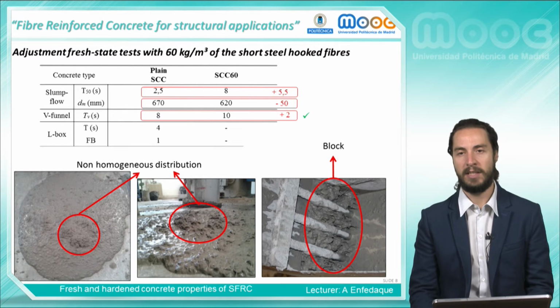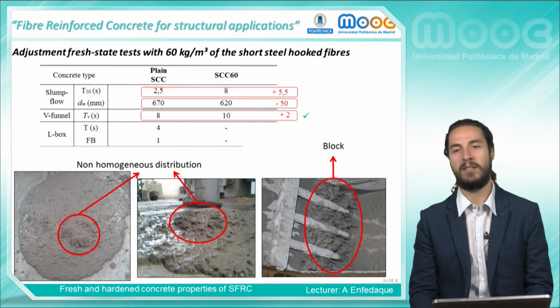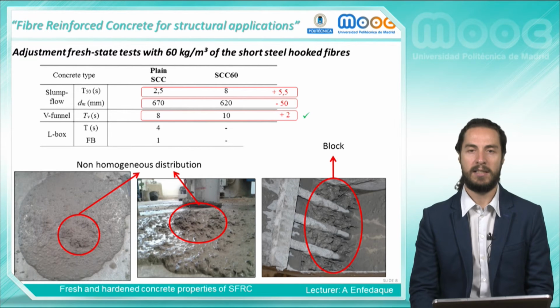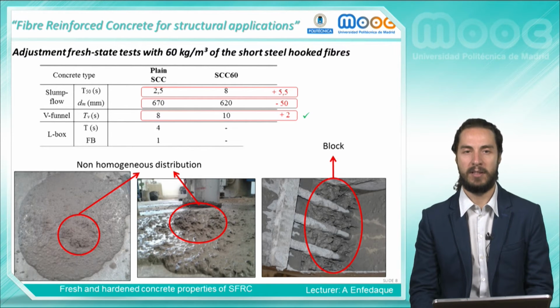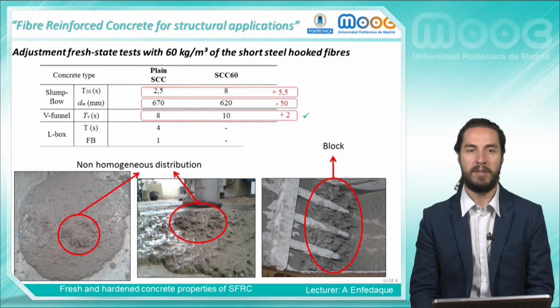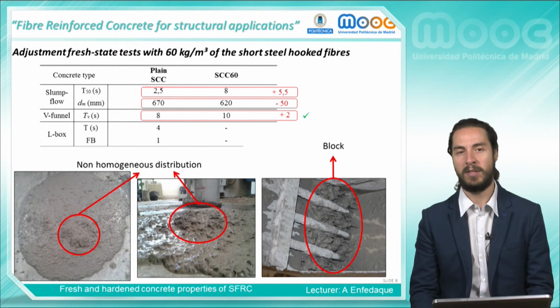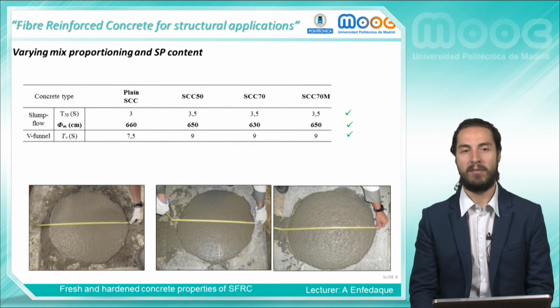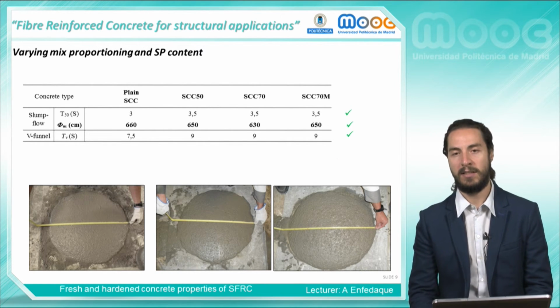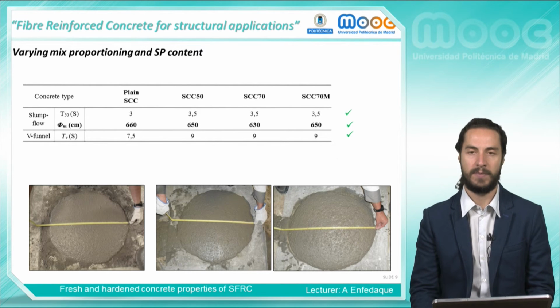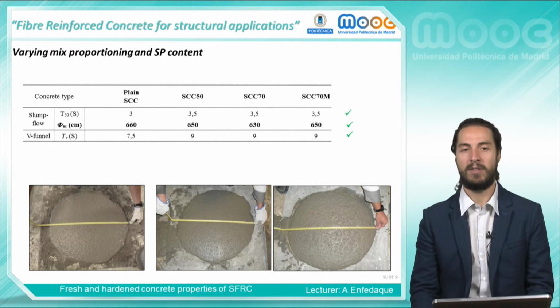Tests for the adjustment in the fresh state of self-compacting concrete are unavoidable. In this case, tests with 60 kg per cubic meter of the short steel hook fibers were performed, having some initial problems as shown in the slide. The addition of these fibers produced a reduction of the slump flow spread of 50 mm, and a poor distribution of fibers and aggregates was found. However, by modifying the aggregate proportioning and the content of superplasticizer, it was possible to achieve the desired results. As can be seen in the slide, with all the mixtures produced, it was possible to assure self-compactability.